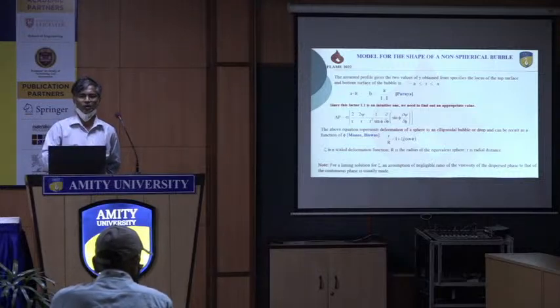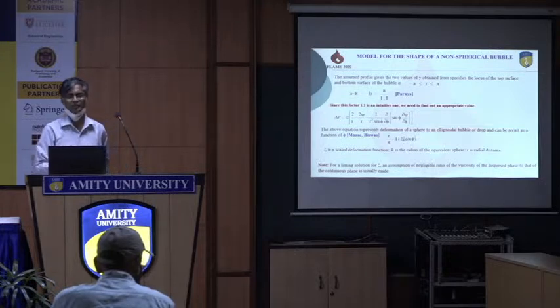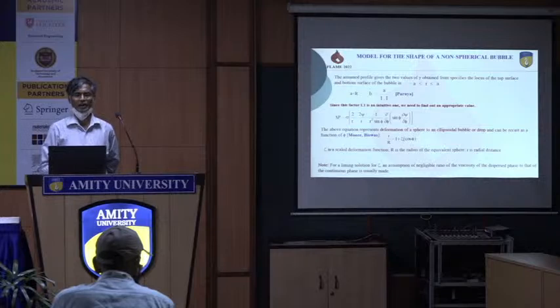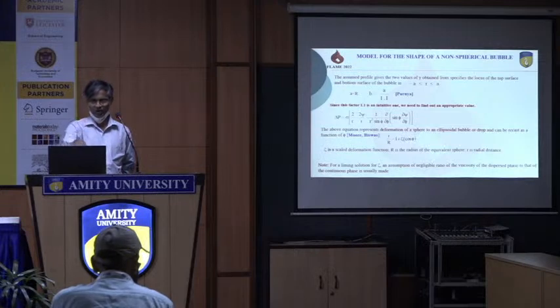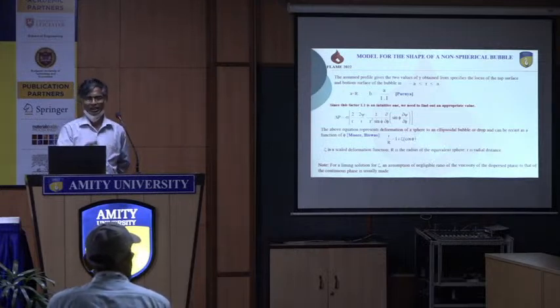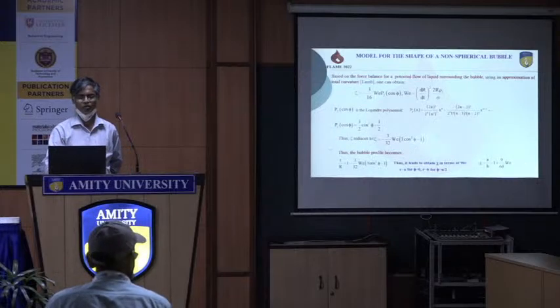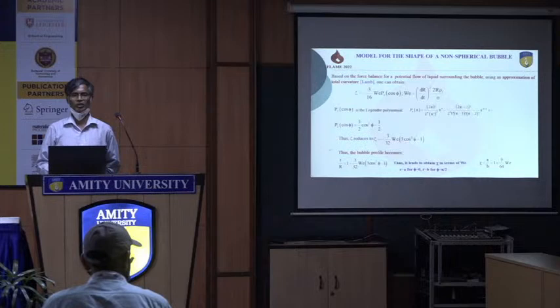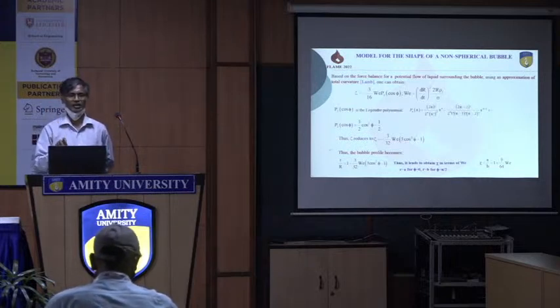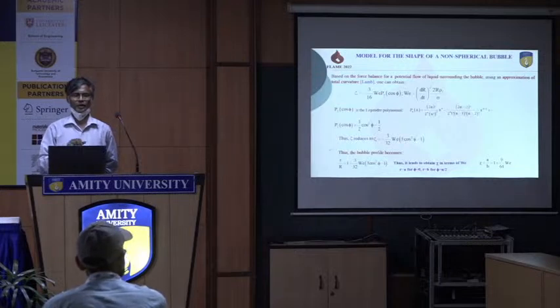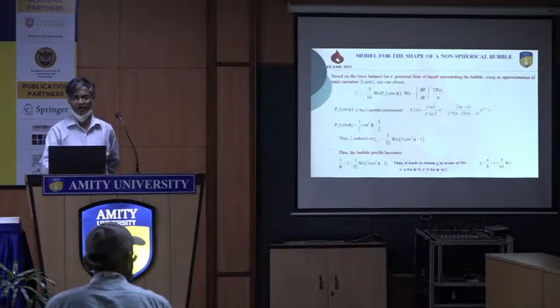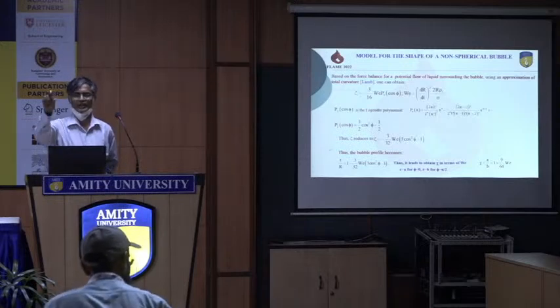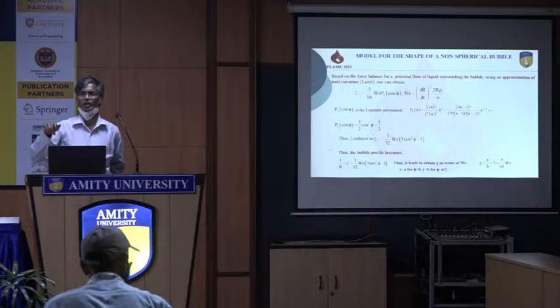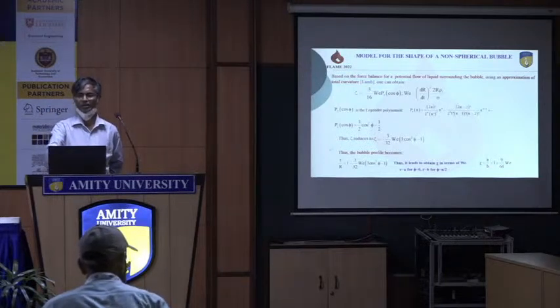Then what we do is transform this particular deformation equation to the polar form, R by capital R equals 1 plus zeta, where zeta is called the scaled deformation function and cos phi the polar coordinate angle. We got this solution in terms of Legendre polynomials that gives the scaled deformation function, which is basically minus 3 by 32 Weber number. For the aspect ratio, we can calculate A and B instead of assuming. This is the new thing we have contributed here.